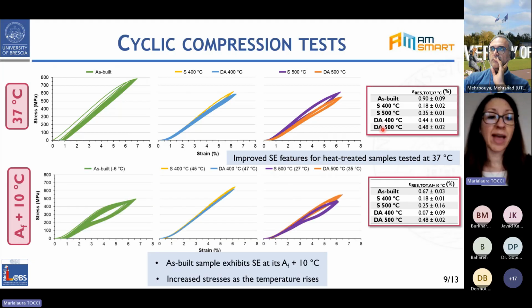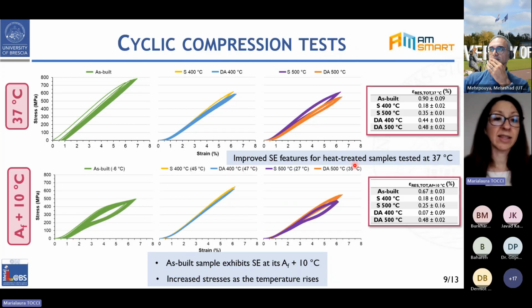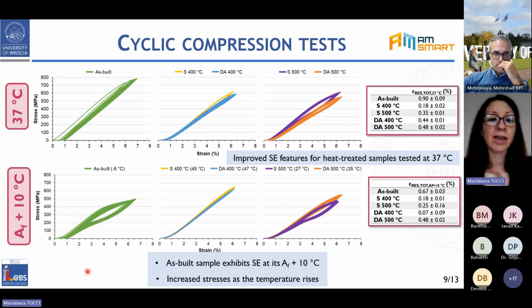On the other hand, when we test the material in more or less the same thermodynamic state, so we place our material in a condition that is 10 degrees above the austenite finish temperature, so a test carried out at a different temperature for each material, for each condition, we can see that the as-built sample put in the correct condition exhibits a superelastic behavior, even though in any case samples after heat treatment perform better, and there's also an increase in stress with the increase of the temperature.